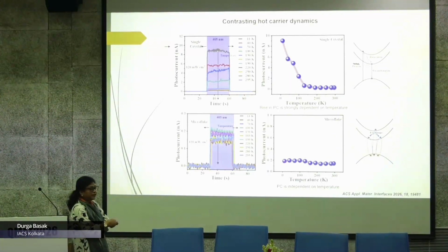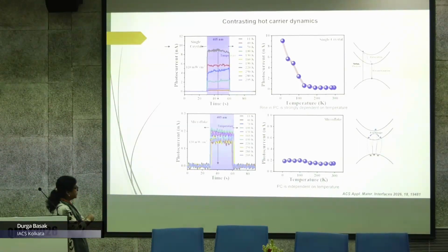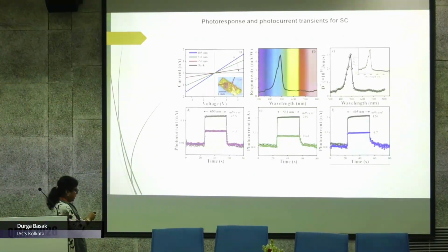So this again is in line with the Raman experiment or the photoluminescence experiment, that strong carrier-phonon interaction happens in this crystal, but in case of microflake it is less. And this particular slide shows you the photoresponse and photocurrent transient of single crystal. The single crystal is responsive to all the wavelengths, 650 nanometer, 532 nanometer, 405 nanometer. As soon as the crystal is shined with 650 nanometer light, the current increases, and when we switch off, the current decreases.